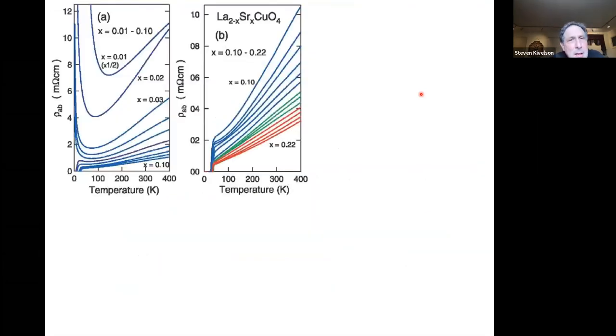Here's lanthanum strontium copper oxide, same material, as a function of doping. Here's our friend, the quantum of resistance. What you can see is that unlike in the previous curves, where the quantum of resistance really meant something, where resistivity saturated or where the resistivity loitered when there was nothing for it to do, these materials really don't seem to care about it at all.